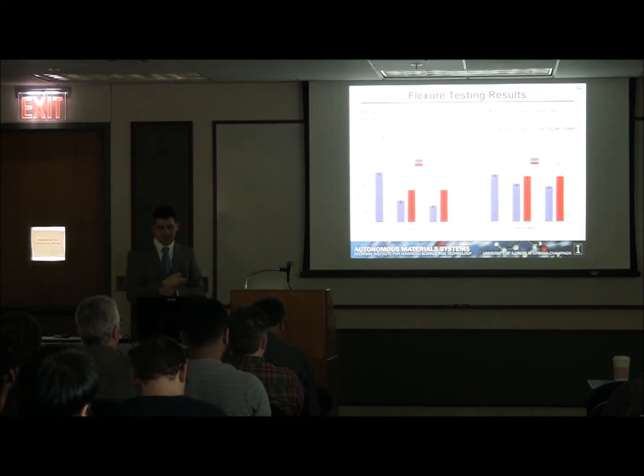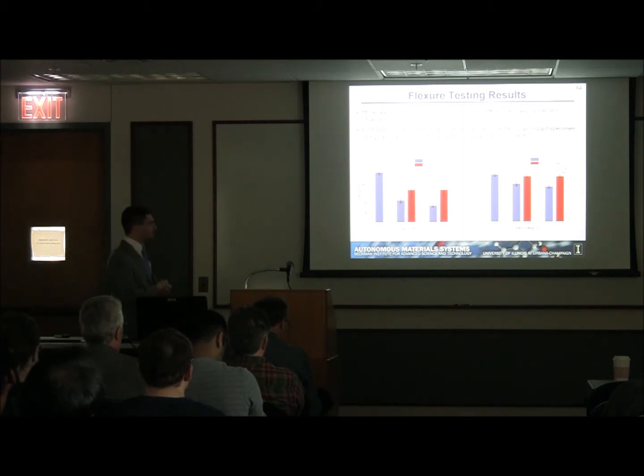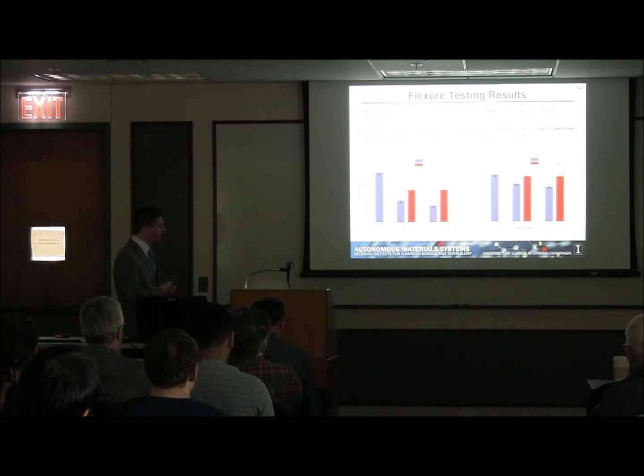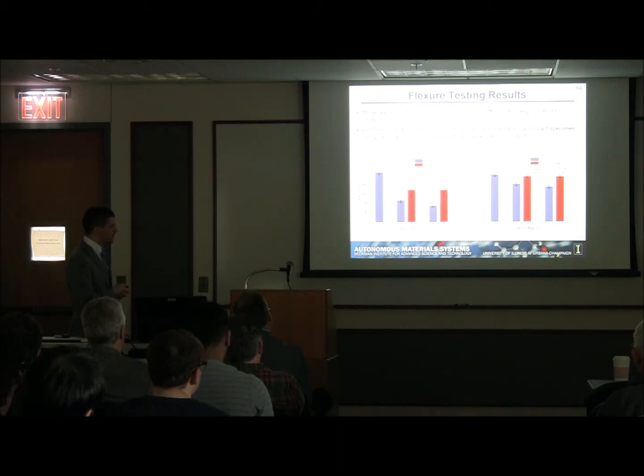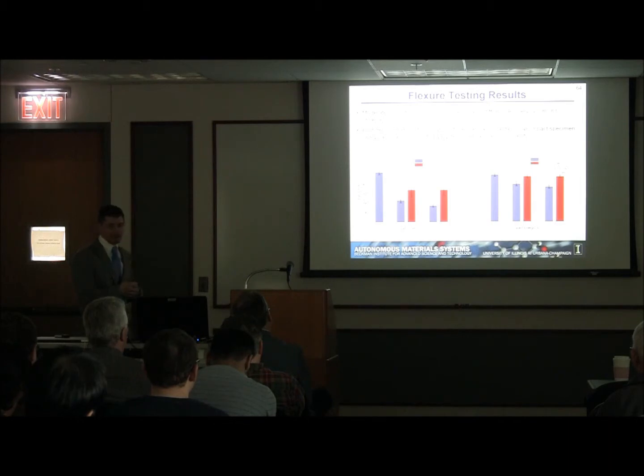If we plot the flexure testing results here, we're plotting the strength and stiffness for moduli with the different impact energies. With no damage, we have a nominal flexural strength of about 520 megapascals. When we introduce damage, we have a reduction to about 220 megapascals with 10 joules of energy. When we fill impacted specimens and allow them to heal, we have a recovery of about 37% healing efficiency. Similarly, for 15 joules, it goes down to approximately 180 megapascals, and when we fill the systems and allow them to heal, we have a recovery from that damaged state of 47%. With the flexural moduli, we see recovery values of about 80% and 83% for the 10 and 15 joule cases.